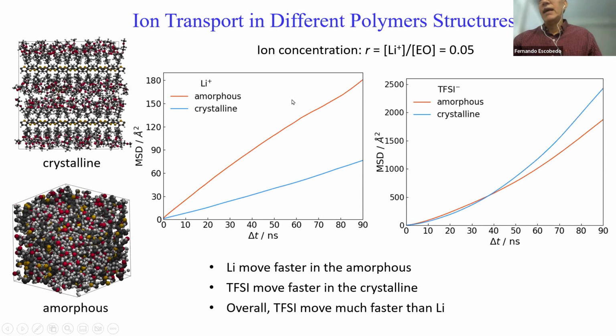If you look at the anion, the TFSI, you see that they are more comparable, but in this case, it travels faster in the crystalline region than the amorphous region. But importantly, if you compare the vertical scales of this mean square displacement, it shows that TFSI moves much faster than lithium ion. So in terms of just the raw total ionic conductivity, the anion contributes more than the cation. But for many practical applications, you care more about the motion of the lithium itself, because that's the active material that maybe you want to move from here to there. So you need to pay attention to the lithium mobility and also the total conductivity.